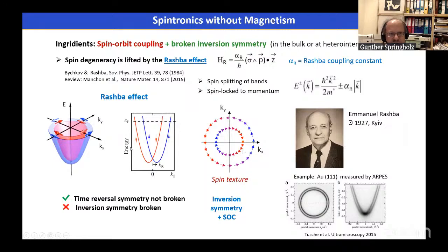With this term, what happens is shown here that the electronic bands, here for an example for the case of a free electron system, split up in two branches, the blue one and the red one. The blue one is the one with the spin up, the red one with the spin down, and they are shifted not strictly in energy, but in the k direction. And this splitting is quantified by this Rashba momentum splitting Kr, which gives the magnitude of how much this spin splitting is.